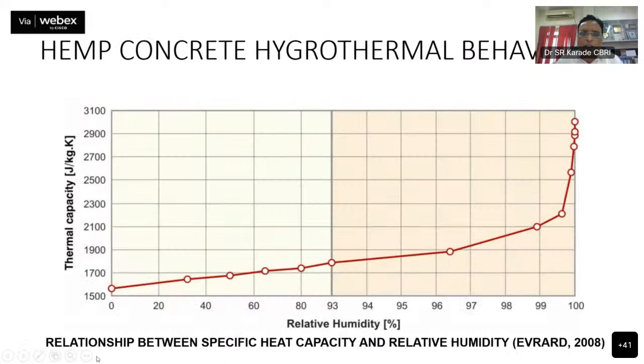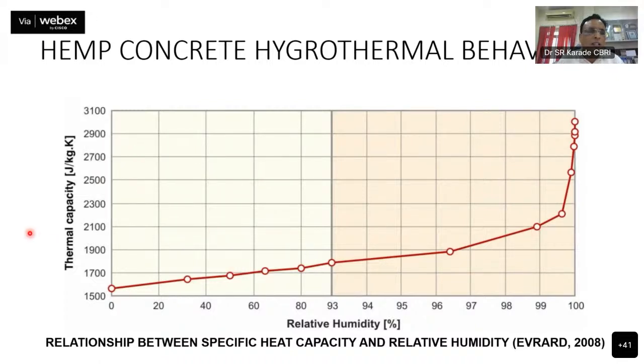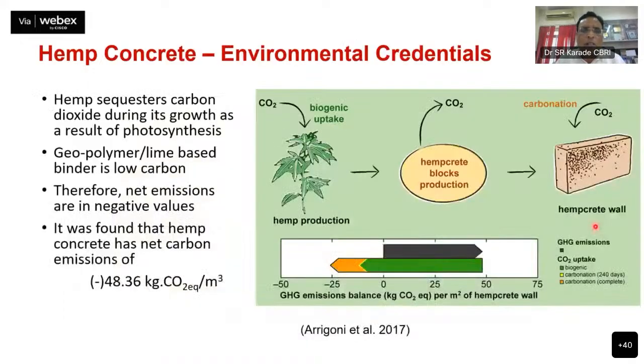As the relative humidity increases, you can see the thermal capacity of this material also increases. That means it absorbs some moisture and provides more thermal comfort inside the room. So these are some salient, very important features of hemp concrete.